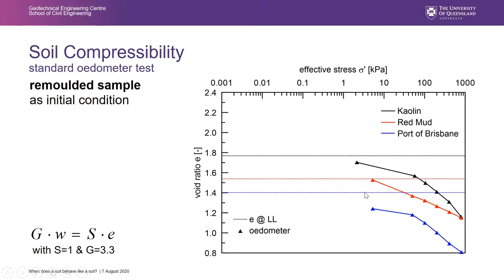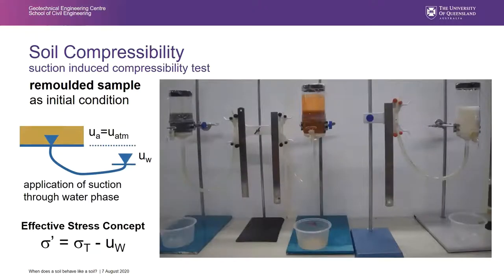So we basically start the test at the condition where we assume that we have soil-like conditions. But now I highlight to you what is the void ratio from the undisturbed samples we have used for the tests. And you see we are far beyond it. So we do tests in a range where basically our soil is not located. So that's why we did another test. That test was developed in our lab, the so-called suction-induced compressibility test.